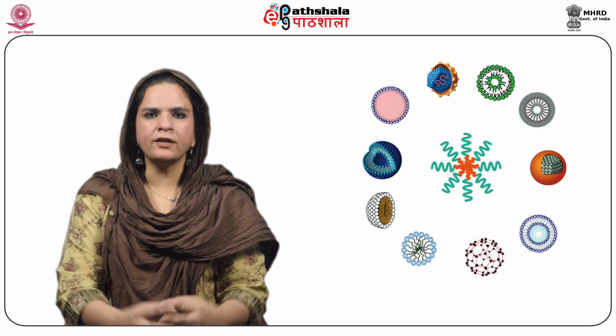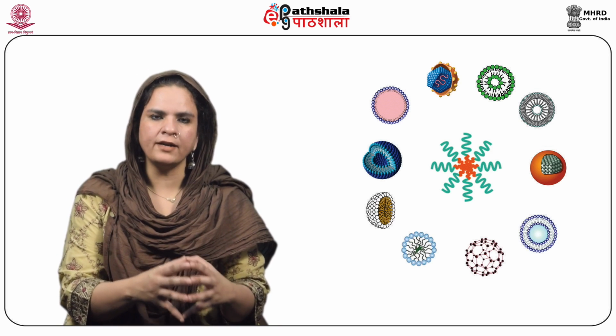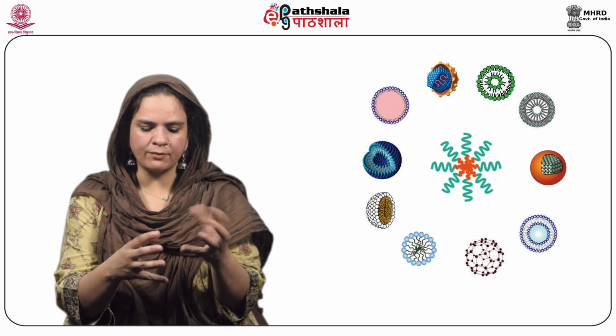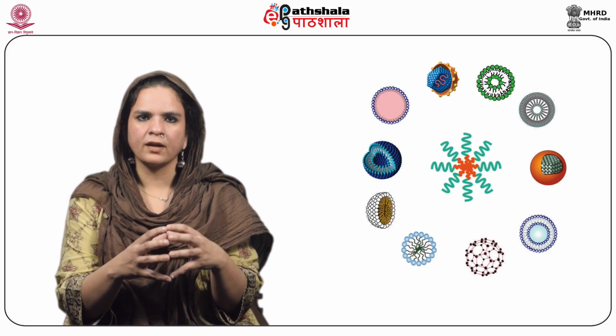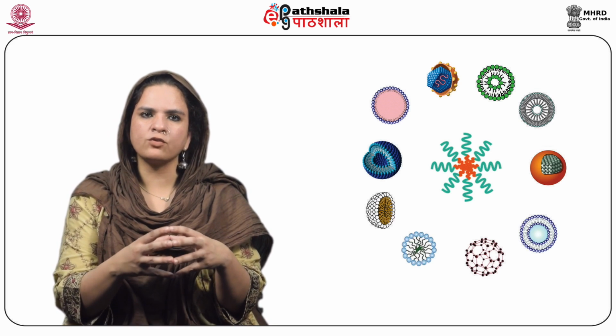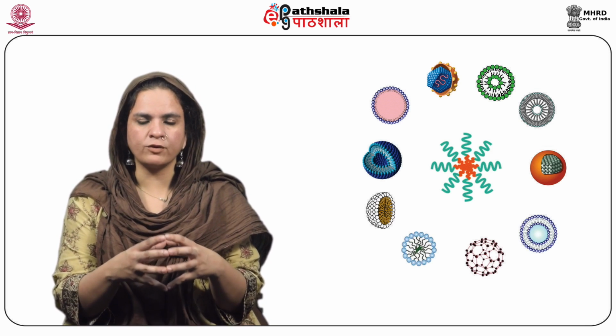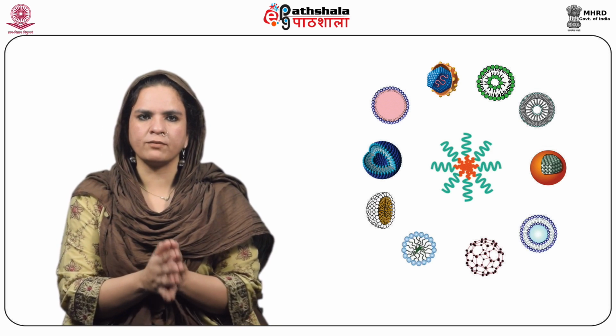Dunn et al. used biodegradable copolymers of DL-lactide and L-lactide with epsilon-caprolactone for preparation of a thermosetting system for prosthetic implants. It is more or less putting something into a cast and then allowing it to take the shape of that cast. Since it requires a free radical producing agent such as benzoyl peroxide in the body for conversion to gel, it may induce tumor promotion. So this is one thing which has to be borne in mind whenever we go in for the usage of such types of systems.